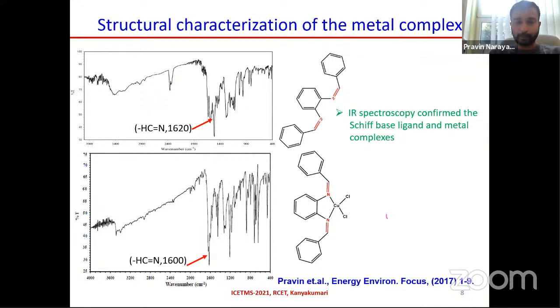This is the IR spectroscopic data. You can see in this data, around 1620 centimeter inverse one, that corresponds to the CH=N stretching frequency. This frequency, after complexation, shifts to a lower value. It's due to the chelation. So this spectroscopy confirmed the Schiff base ligand and complex formation.